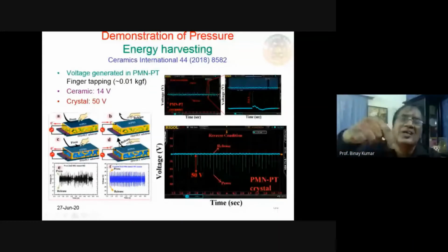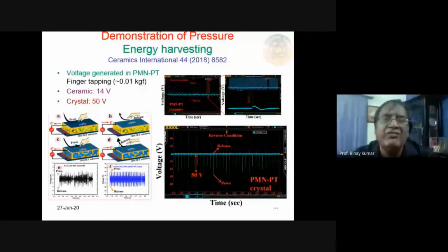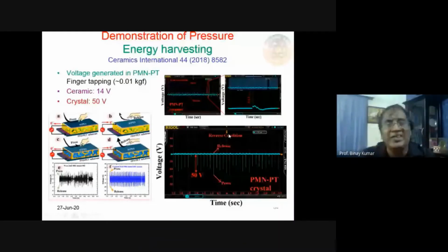Just to demonstrate a few of them. What we do, we take the material. Normally we can put a crystal as such and just hammer it with some hammer, or just by finger tapping also. The smaller the force, the higher the output is actually desired. So actually we have used our finger to tap it, and you can see that if we have a PMN-PT ceramic, this voltage is going up to 13-14 volts. It is an open circuit voltage. And when we put the same material in crystal form, voltage up to 50 volts can be generated just by doing nothing. I'm just putting my finger on the material and we are getting electricity.